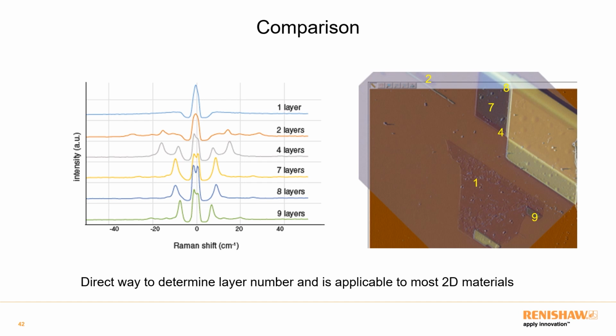Here I'm focusing on the low wave number region, and you can see for a single layer of material there is nothing in the low wave number region. That's because there's one layer and there are no other layers of atoms to move against it, so you don't see any bands. There are, however, bands higher up, so I can still confirm there is rhenium disulfide here. As we go to higher and higher layers, we have bands. The band position changes, and broadly, they start to move down closer to the laser line, so you have this trend coming inwards.